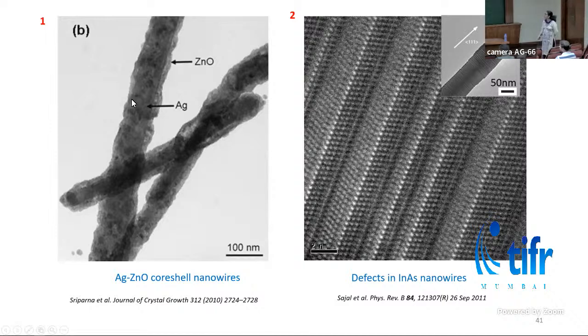As I mentioned, it gives you the Z contrast and diffraction contrast. Here, in this silver nanowire, silver being high Z, has a higher atomic number. That's why we can see that the center portion is silver. And of course, we can do EDS line scans, or we can confirm this using elemental analysis also. Zinc oxide being a low Z material, we see a lighter gray contrast in zinc oxide.